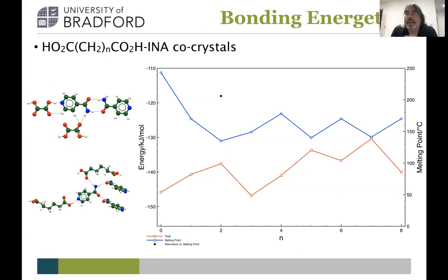And if you do an energy framework calculation on it, these are the three strongest interactions in the whole structure. So what I've done is I've taken the calculated energy for these three bonds, summed them together, and then plotted that out. That's the red line against the length of the aliphatic chain in the compound. The only one that differs is pimelic acid, which for some reason doesn't form the dimer. It forms the same two hydrogen bonds, but forms them to two separate molecules and forms these different chain structures through the system.